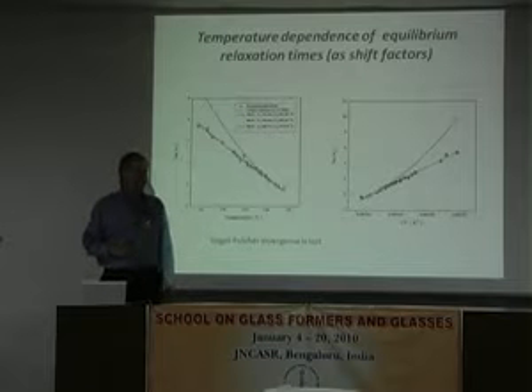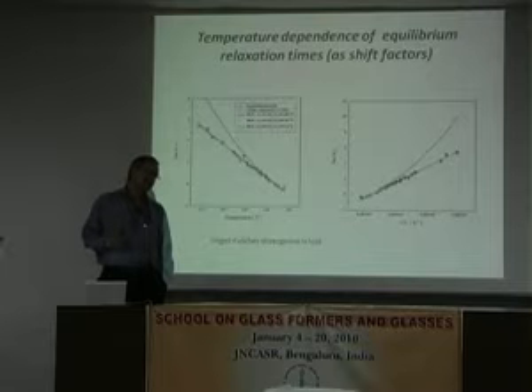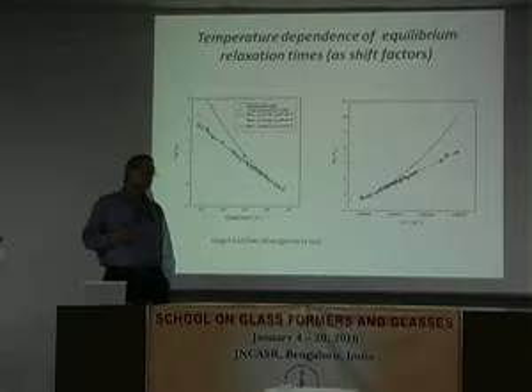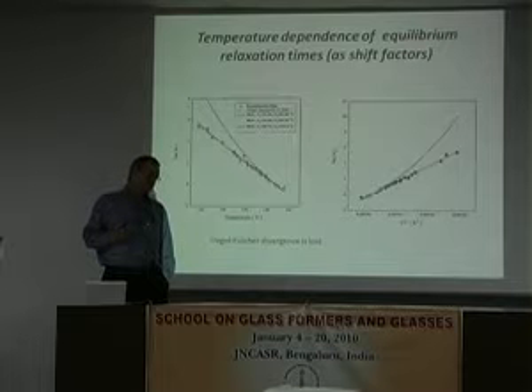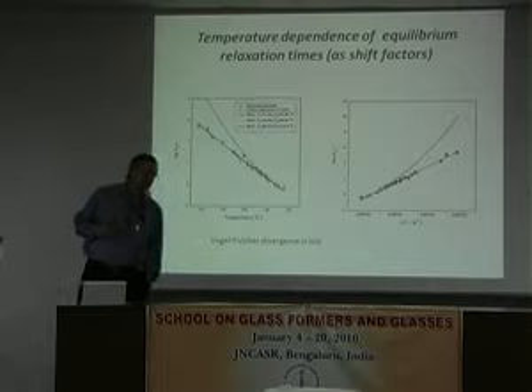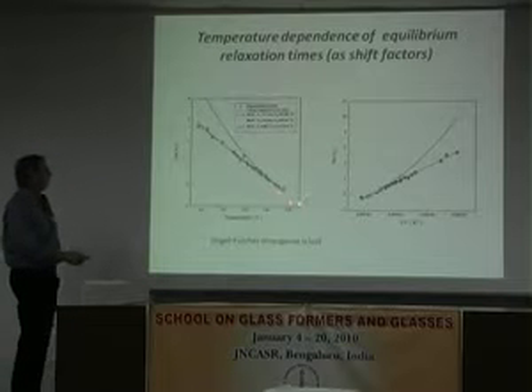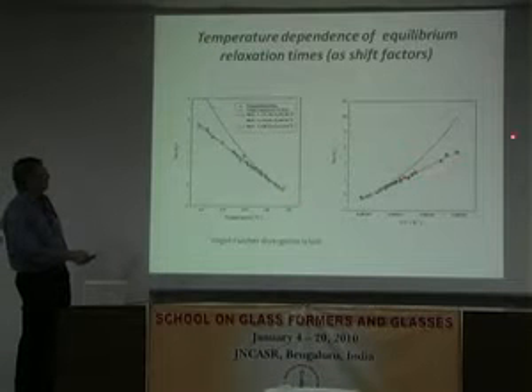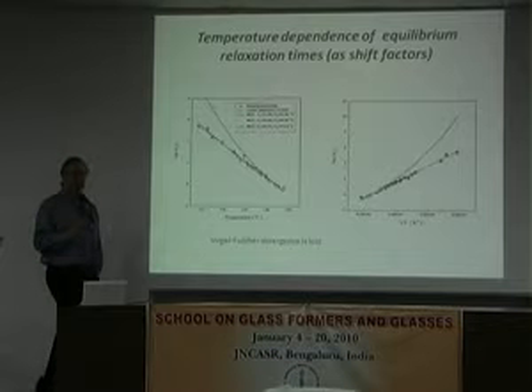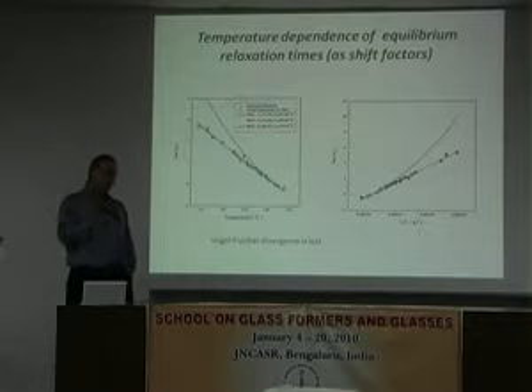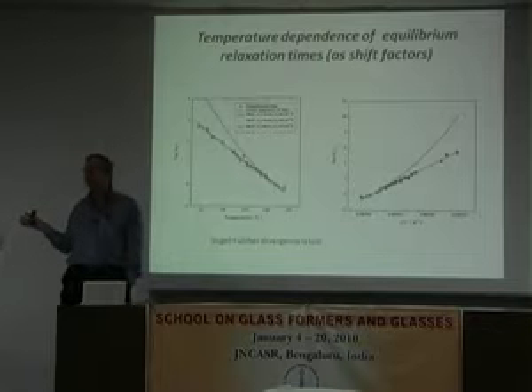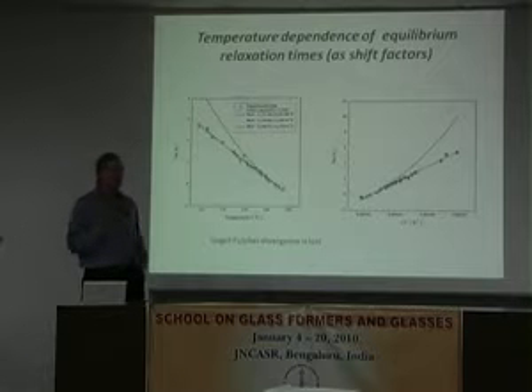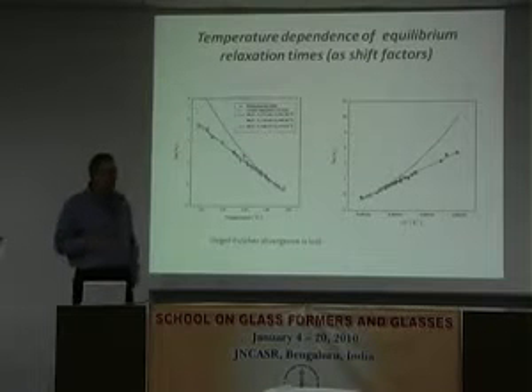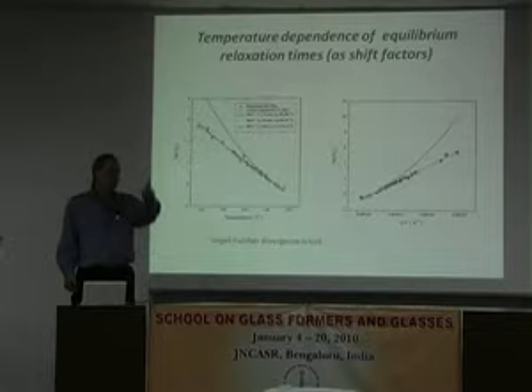Right. So what's not clear is that if the data is departing from a Vogel-Fulcher fit, you don't jump to the conclusion that it's going back to Arrhenius, right? There are a lot of other possibilities. Well, except this is a pretty good straight line in that range. No, you're absolutely right. But it's consistent with the idea that there's no need for a diverging length scale, or at least not one that's diverging so rapidly. Yeah.